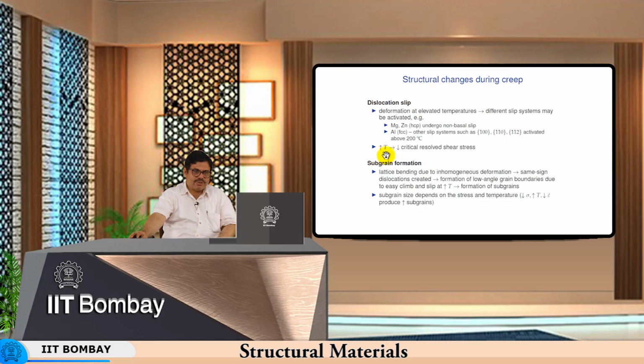So, increase in temperature decreases the critical resolved shear stress. That is quite obvious, because the material softens as the temperature is increased, and therefore the critical resolved shear stress also comes down. And so with this you will get different other slip systems also getting activated. Then there is sub-grain formation, where lattice bending due to inhomogeneous deformation takes place. Same sign dislocations are created, and low angle grain boundaries form due to easy climb and slip at high temperatures, which leads to formation of subgrains.